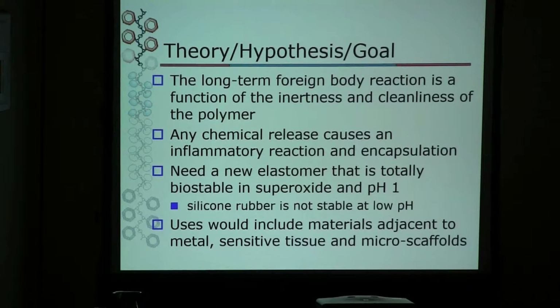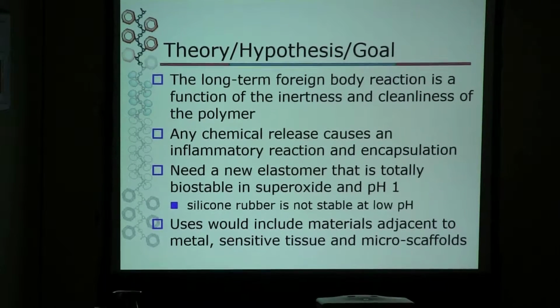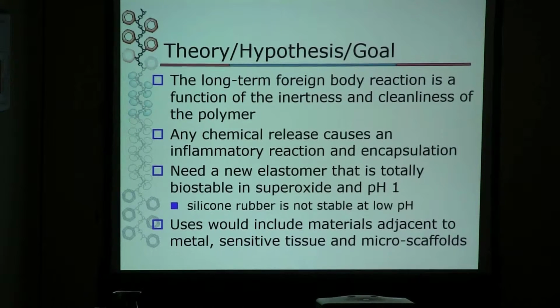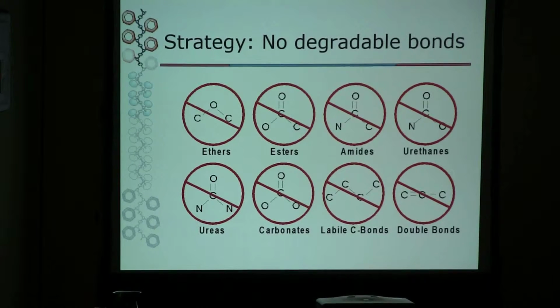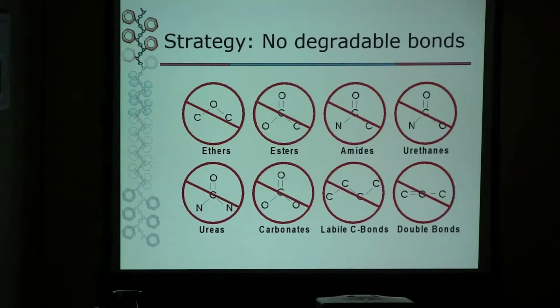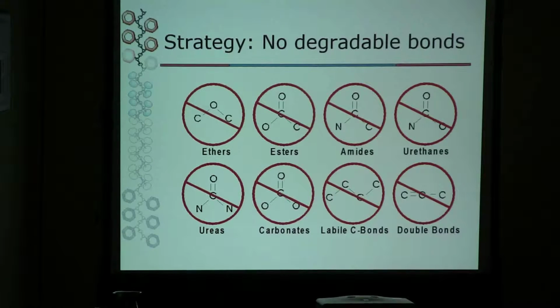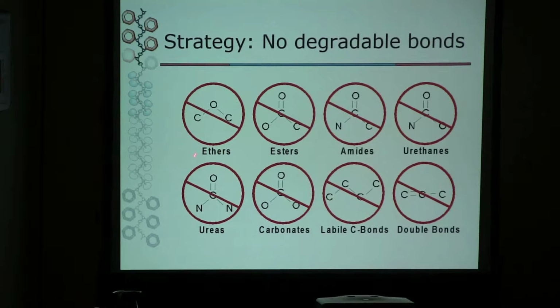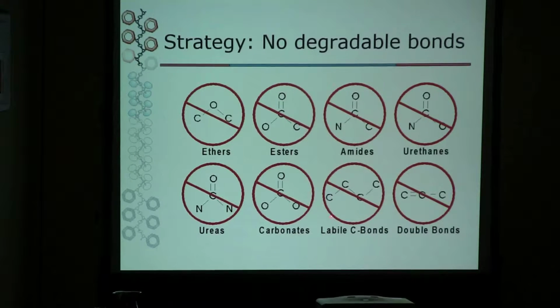If you had such a material, you can now use it against metals, and metals cause metal ion oxidation, and you can use it in sensitive tissues of the body and as microscaffolds. So the strategy is really simple. You get rid of all bonds that are capable of cleaving in the body, and I was going to apologize for getting into the organic chemistry, but after what I listened to the last 2 days, I don't apologize anymore. So you have to get rid of ethers, esters, amides, urethanes, ureas, carbonates, carbon-carbon bonds, and double bonds. And for those of you who have worked with polymers, there's really not much left.